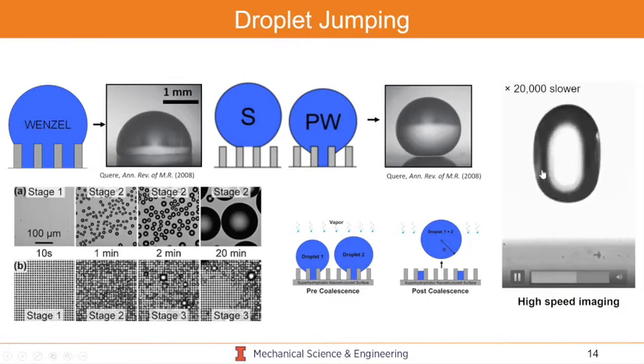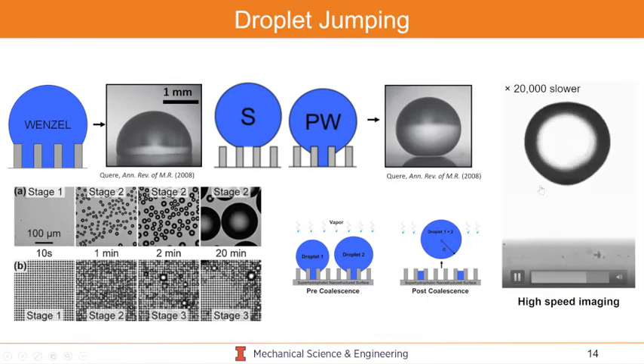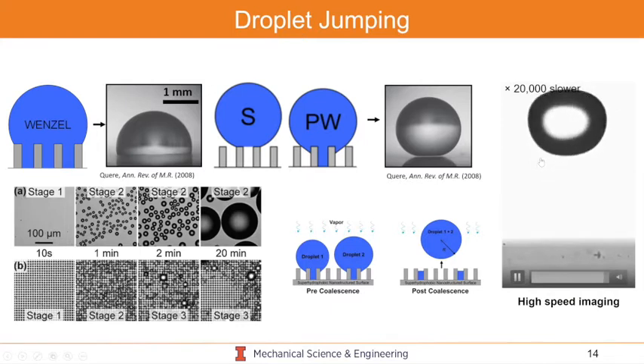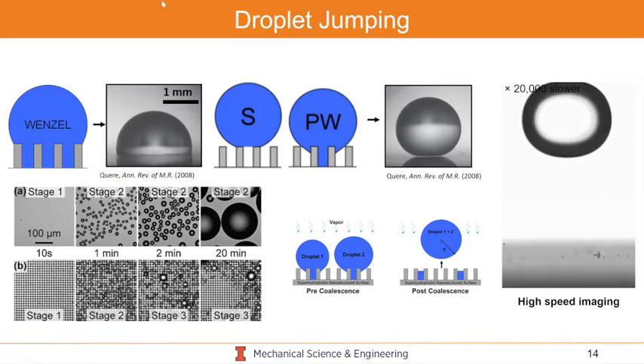And the way this process works, and the reason it could actually happen, is if you think about just an energy balance, the surface energy of two separated droplets is larger than the surface energy of one combined droplet. And it's this difference in surface energy that actually manifests itself into kinetic energy. And that kinetic energy is the energy of jumping, or the velocity that this droplet takes on once it departs from the surface.